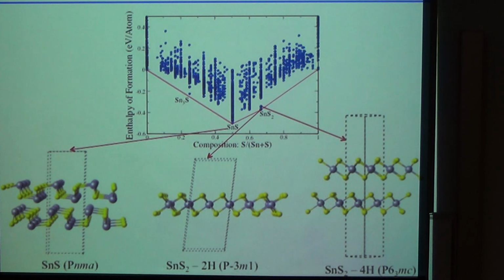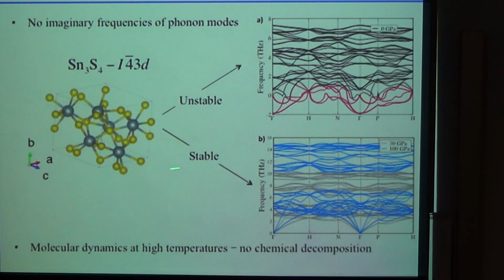Especially at ambient conditions. Then there is the 1,2 compound, but then we predicted a new compound that I'm going to talk about later on. Once we predict compounds, we want to make sure that this compound is stable. As a rule, for thermodynamically stable compounds, we didn't see any cases where we predicted a thermodynamically stable compound and it was unstable. If it's unstable, you need to search again, explore the same stoichiometry, and find the different polymorphs of the given material. Okay? But you look at the phonon spectra, so these are the vibrational frequencies versus the Q vector, right?